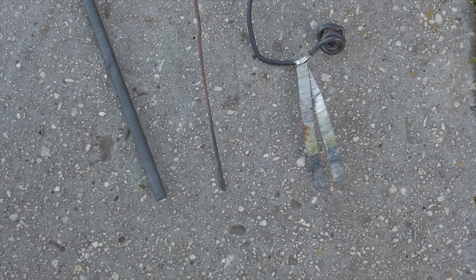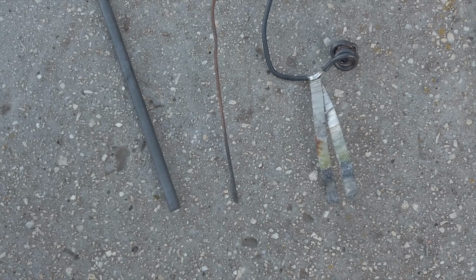Now that we've actually finished the reaction and I've packed up the cell, we can have a look at the 3 electrodes we ended up using for the process. First of all is the nickel cathode that we started with. Interestingly, it did actually work in generating lithium, I found out, because after taking the nickel out of the cell and putting it in some water, there was a very clear generation of hydrogen bubbles. So we did have lithium actually stuck onto the surface of the nickel there, but we just weren't able to get it to bead together. Exactly what we expected to happen, pretty much.